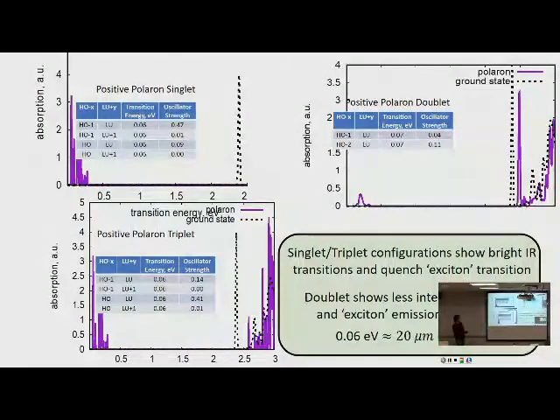We see that's pretty bright. For the triplet, you get 2 that have pretty moderate oscillator strengths for that transition, and same deal for the positive. Whereas in the doublet, you have some small IR contributions, but you also still have a bright exciton transition, or what you normally see go across the band gap.